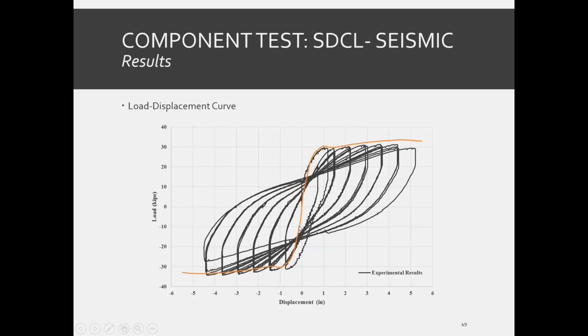Based on the experimental results, we can conclude that the failure occurred at the first cycle of 7 delta Y by fracturing one of the column longitudinal rebars, and this caused a 20% decrease in the capacity of the column. At this point, the test was terminated. Based on this, the ductility level of the column is concluded to be around 6.